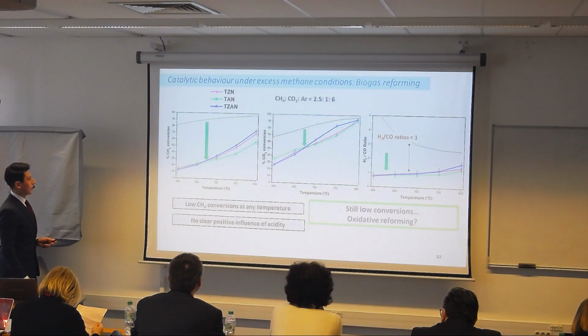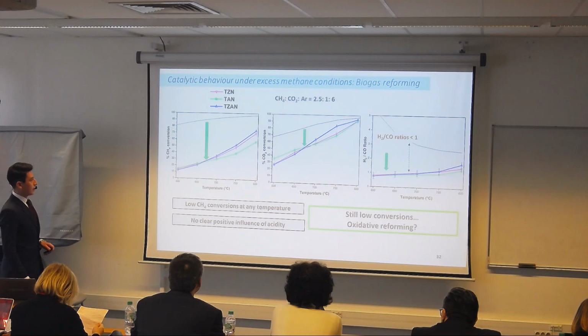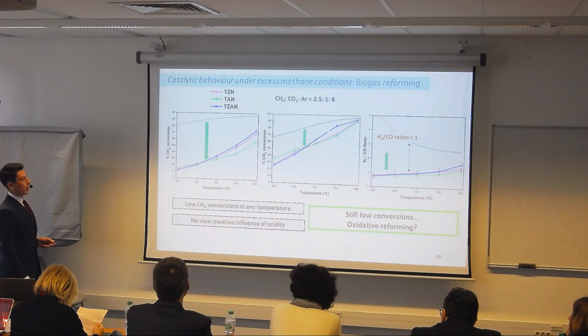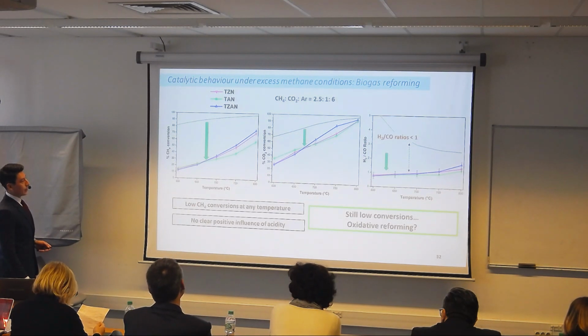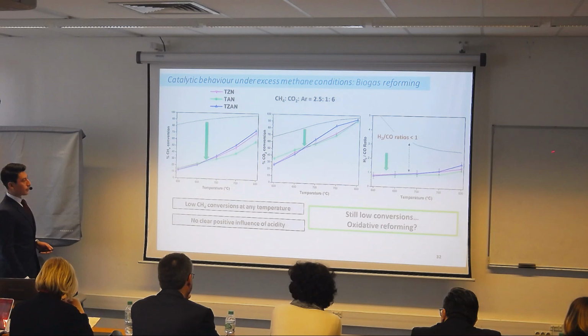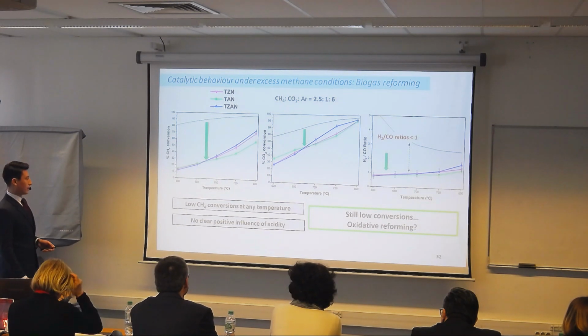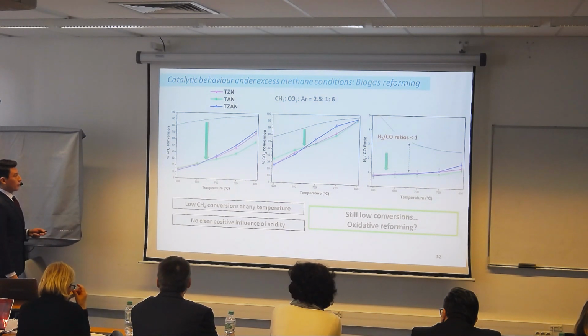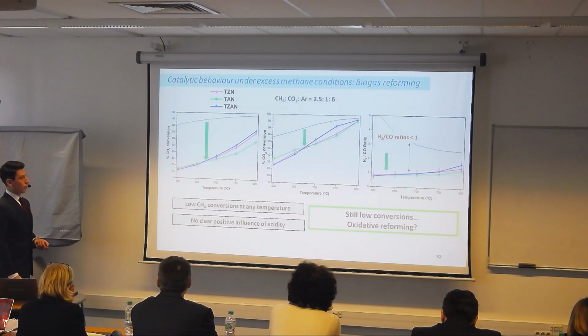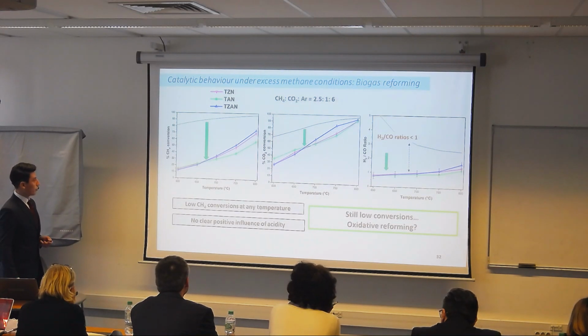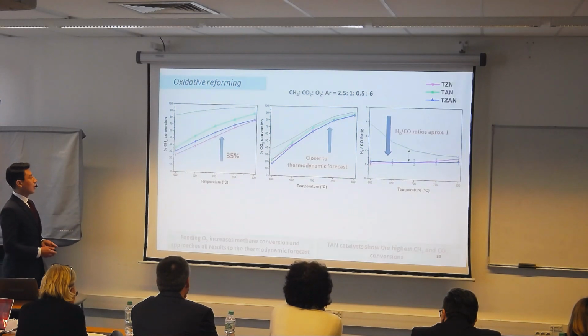Initially, we have the three catalysts prepared, and we can see that we have a very low conversion at any temperature. That also happens for H2/CO, and the ratio is just getting over 1 at high temperatures. So we have no clear positive influence of the acidity. Also here we are still having low conversion of methane.